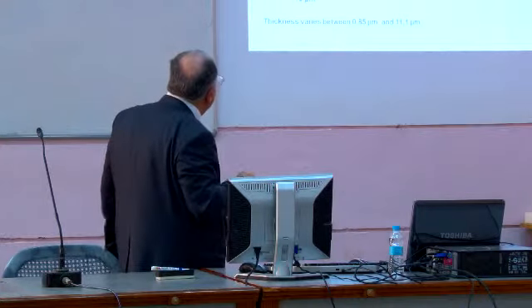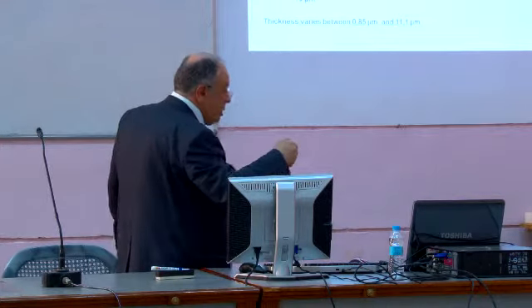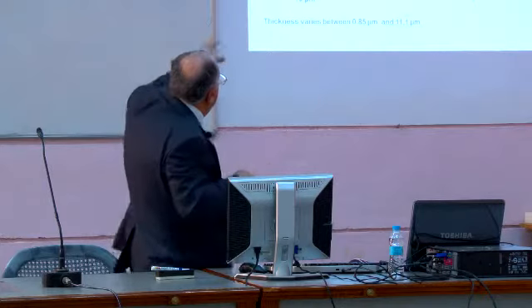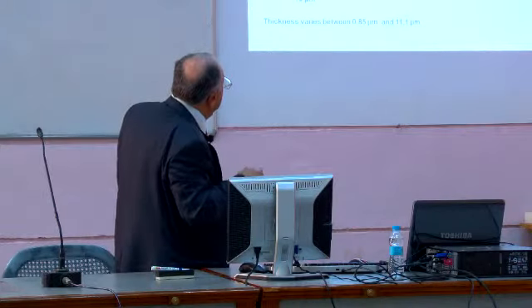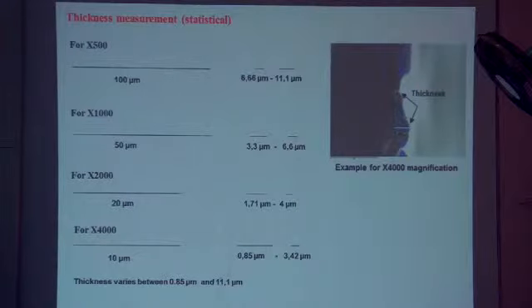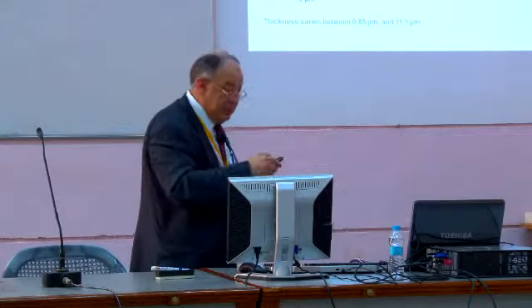So we did some more statistics, and we measured the layer thickness at different magnifications, arriving at thicknesses varying between 0.85 and 11.1 micrometers.